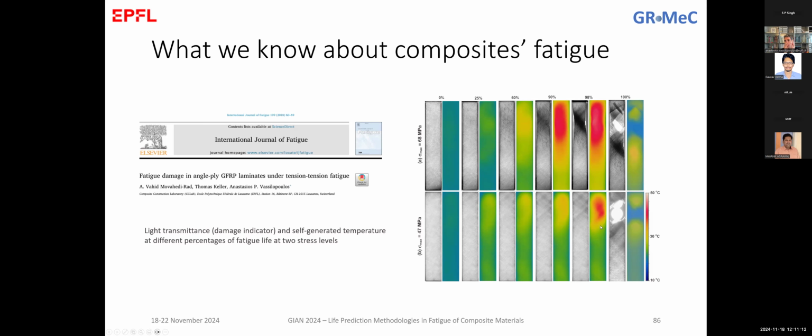You know, friction is increasing when we have damage. It means that we have more roughness, so the friction with the fatigue loading is higher. That's why we have these effects. So here we've shown that it is possible to monitor the damage evolution on the material by using optical methods like those presented here.